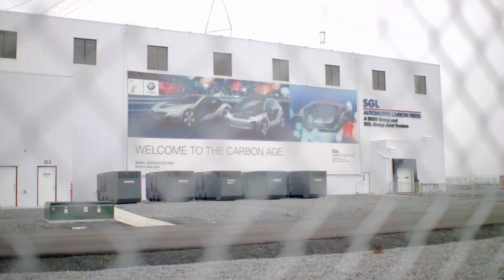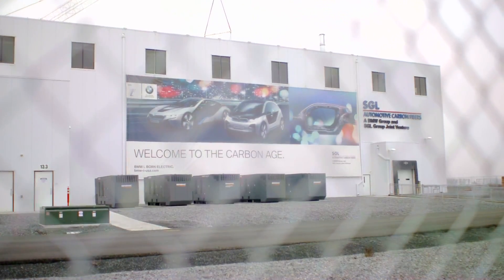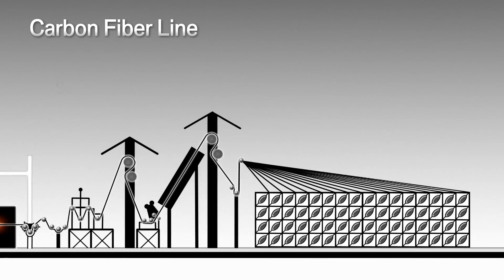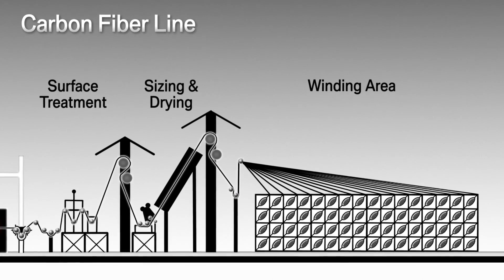Back to production. What happens to the fibers after carbonization is a manufacturing secret. After carbonization, the material really has no functionality — it's sterile at this point. So in this process we etch the outer skin of the material to allow it to bond with the resin system in later applications. After this, we size the material for usability and handleability.